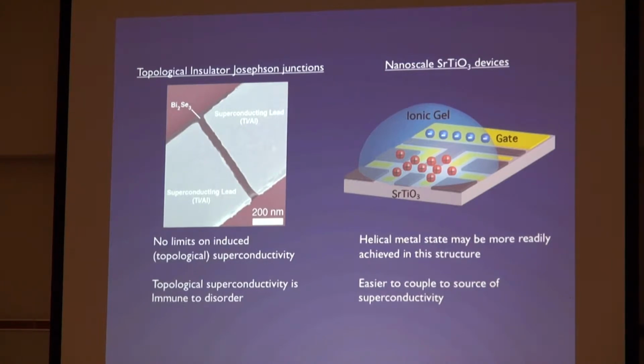I'd like to just highlight some of my work from two systems where I think hold a lot of potential in really knocking down whether Majorana exists or doesn't exist in these systems. One is a topological insulator Josephson junction. And it turns out in this setup, theory has shown that there's no real limits on the size of the topological superconducting gap you can create. And that gap is immune to disorder that we all know exists in these devices. This is not true in the one-dimensional case that I just showed. That has a very sensitive relationship with disorder. The other is looking at complex oxide materials.